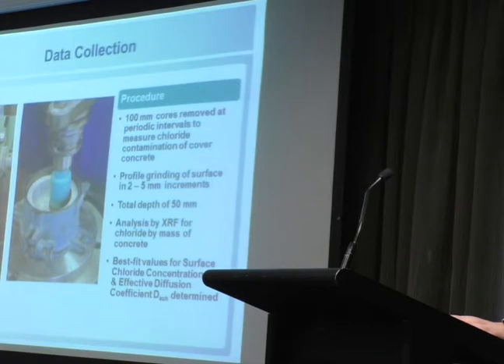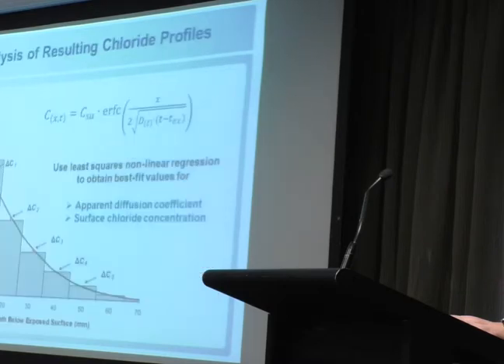And the data collection, although the concrete was characterised in various ways, the main effort went into removing cores at periodic intervals and then milling the concrete surface as a function of depth and analysing that for chloride content. And as has already been talked about, you get a plot of chloride concentration versus depth, and using the solution to Fick's second law, you can characterise that in terms of the surface chloride concentration, so the theoretical extrapolation of your chloride concentration to the Y axis, and also the diffusion coefficient, which is effectively the shape of the curve. And that's just done through non-linear curve fitting, so simple mathematical procedures.